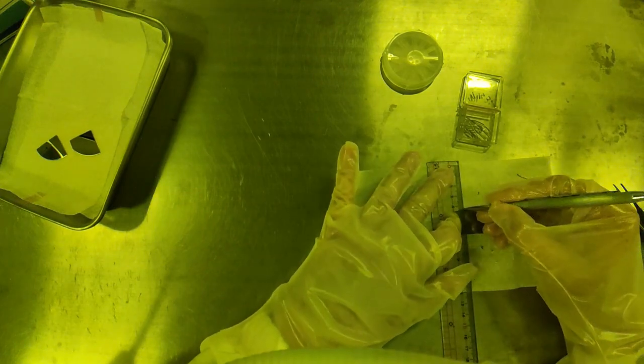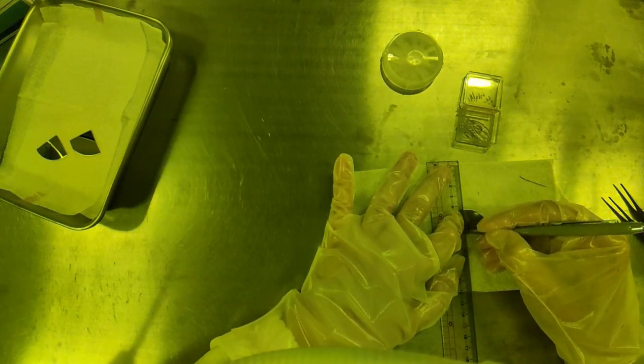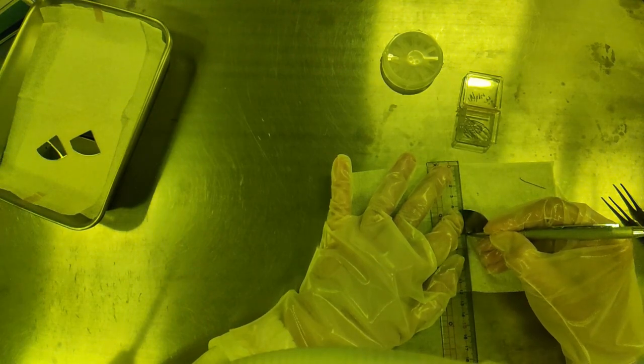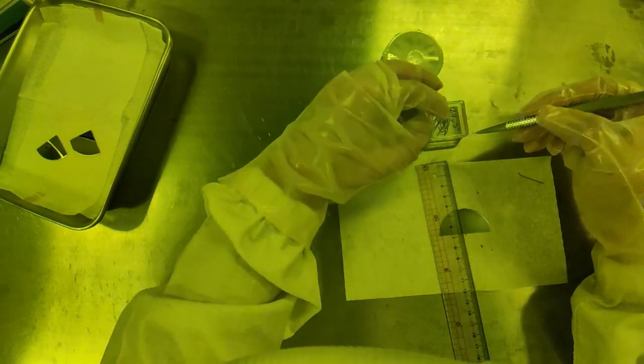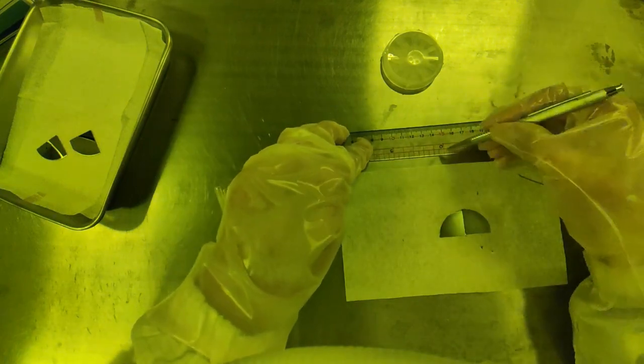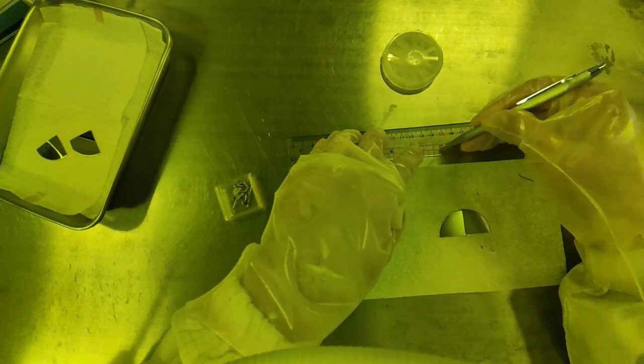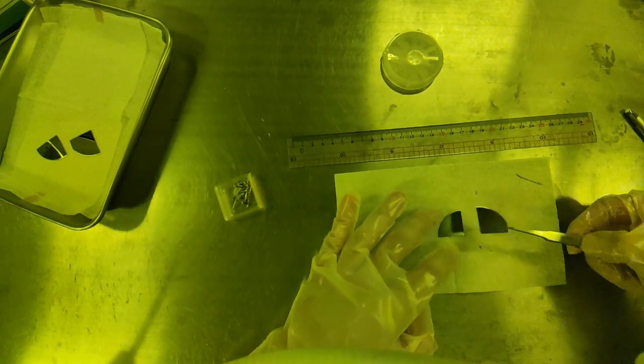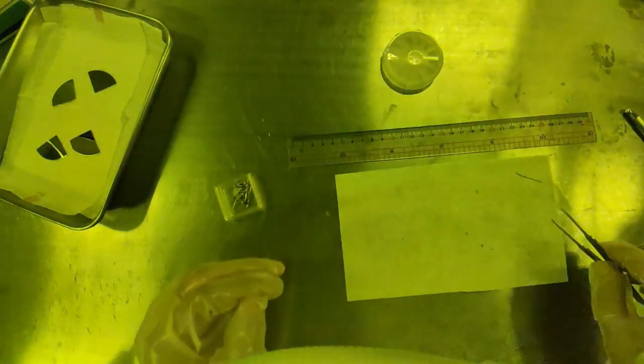I have a holder plate here. And I'll just put it proper side up in the holder. And I will show you again how to fast cleave the silicon. So, your goal is to make a long, even cut the whole way. So, you start, you really have to start from the corner. And then when you are going down, like on the bottom end, you have to press hard. And when, for example, like, I can explain it like this. So, if this is the side of the wafer, the long one. And when you go to the side and you want to crack off the small bit here, small portion, so you press really hard and let it slide off the side like this. And then it will crack. And the silicon actually cracks really beautifully like this. No problems whatsoever. Here it is.